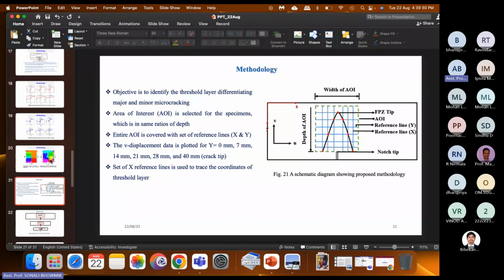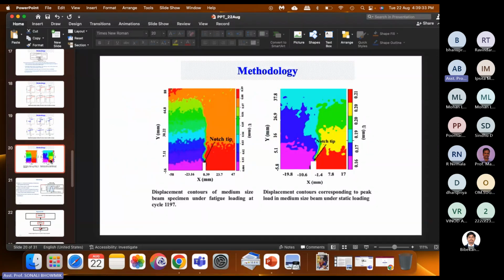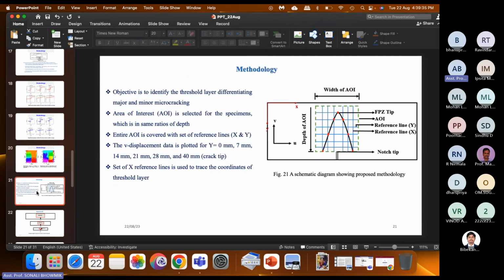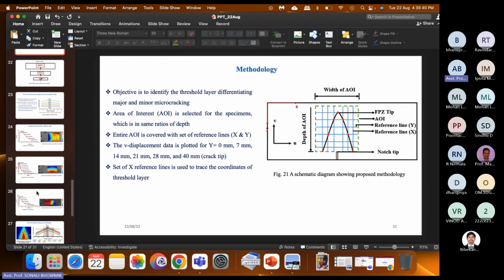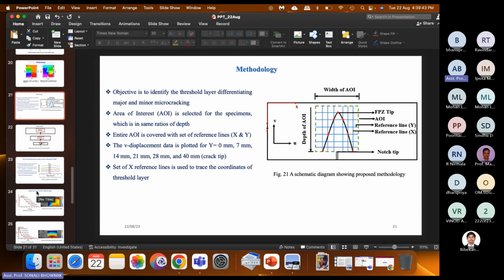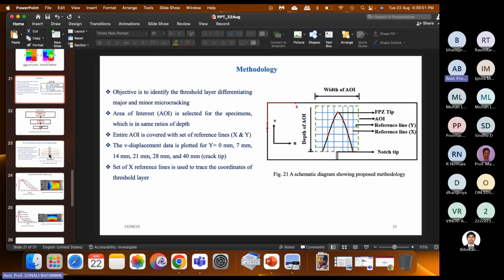Now this is about the fracture process zone length, and this work can be carried to the fracture process zone width, where methodologies have also been developed, and it has been verified with the fracture process zone length that this methodology is working fine. So why is it important to find out the fracture process zone width? Because it gives us an accurate estimation of the fracture process zone size.